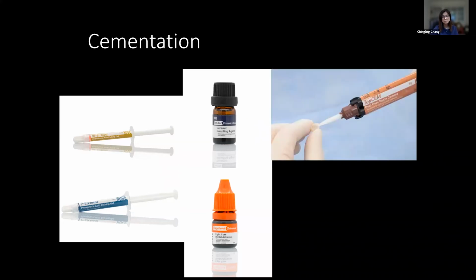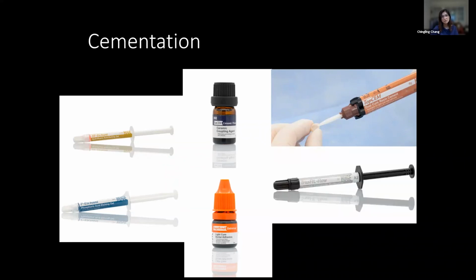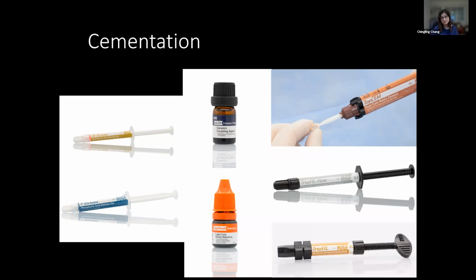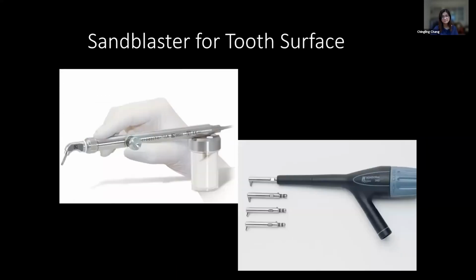And we can use dual cure resin cement for cementation. We can also use flowable composite or regular composite for cementation. It really depends on personal preference because everybody's different. And for the tooth surface, we require sandblast.